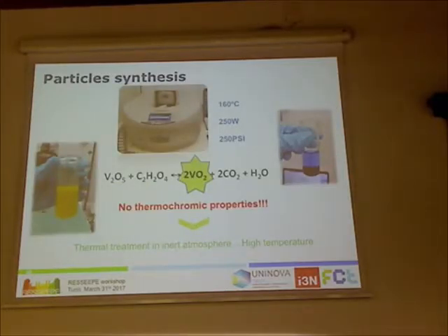So in our case, we go from hydrothermal synthesis, creating pressure and temperature inside the autoclave. You start from V2O5, oxalic acid, and in this reaction inside the autoclave you get the VO2 nanoparticles in suspension, along with some subproducts of the reaction. But if you take this powder after the reaction, they have no thermochromic properties.